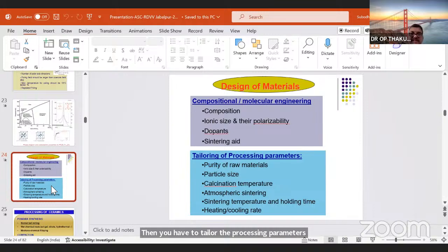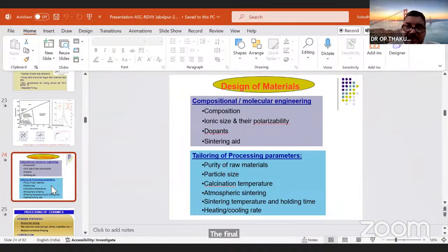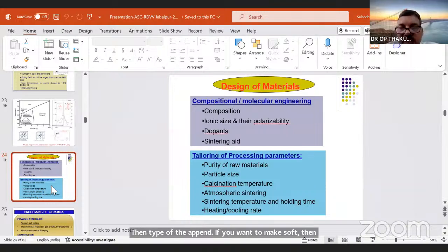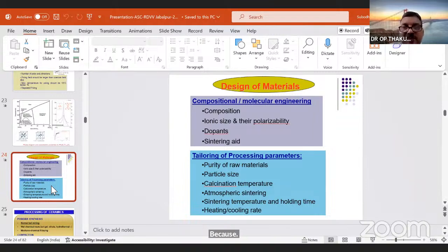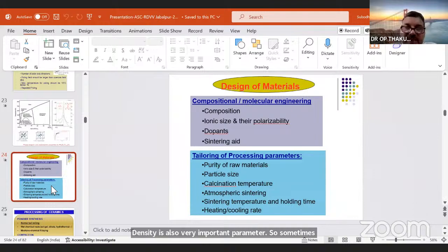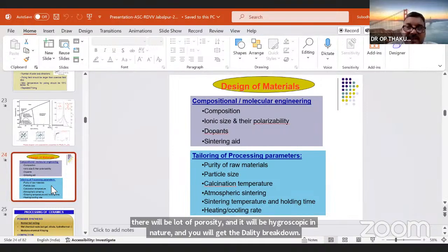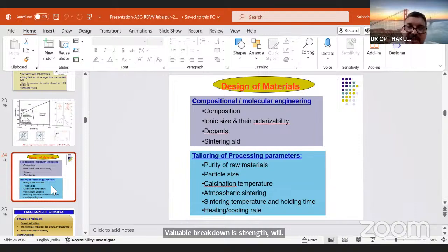When we talk about compositional engineering, the final property is majorly affected by the starting composition, its purity, the particle size of the raw material, then the ionic size of the dopant and polarizability. Then the type of dopant: if you want to make it soft, you choose one kind of element, and if you want to convert it into hard, you choose another kind. Then the sintering aid, because density is also a very important parameter. Sometimes people use liquid phase sintering or some kind of sintering aid to densify the material further. Otherwise, there will be a lot of porosity, it will be hygroscopic in nature, and you will get dielectric breakdown. The dielectric breakdown strength will drastically degrade if you don't have a good density ceramic material.